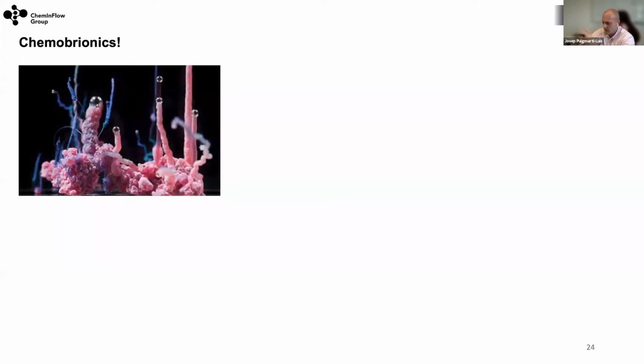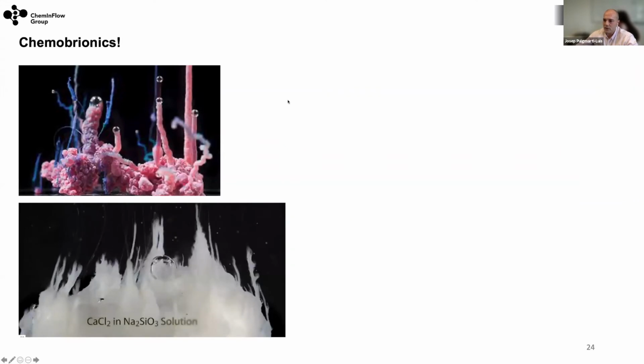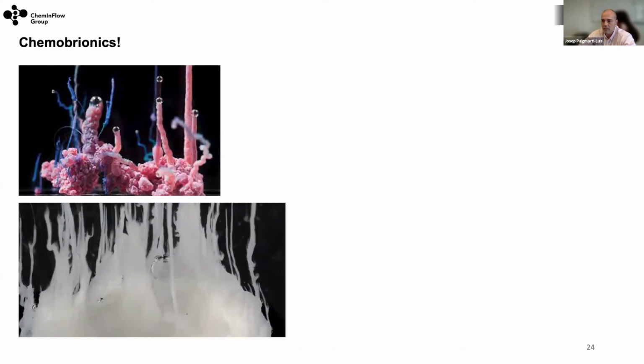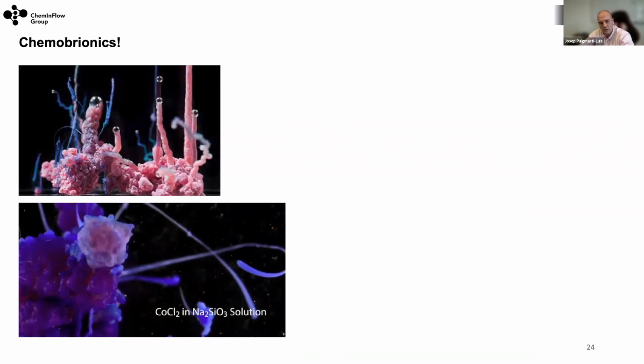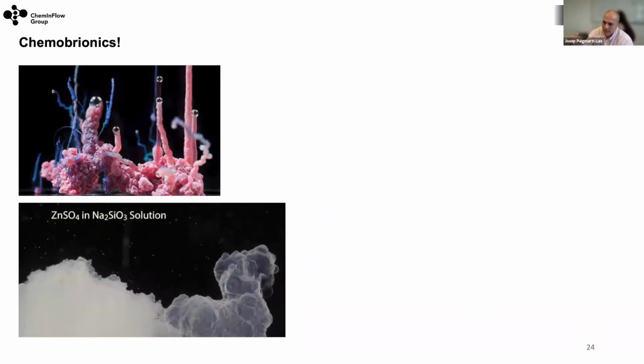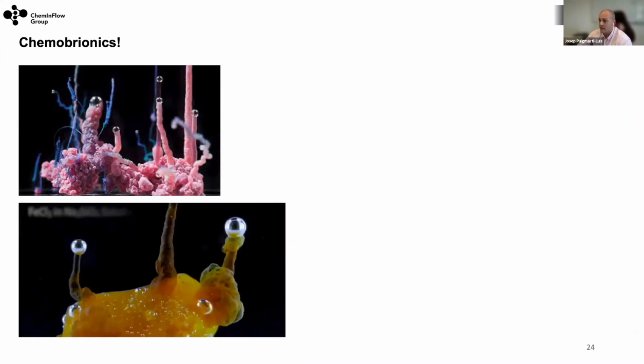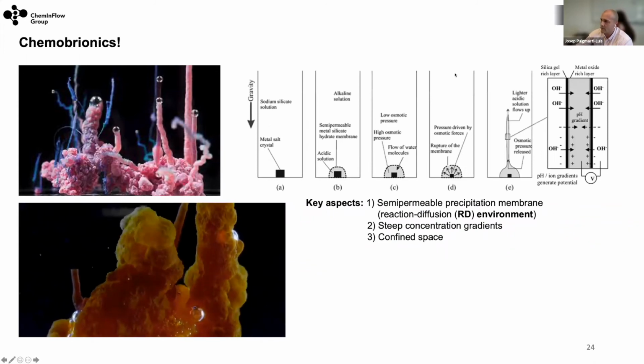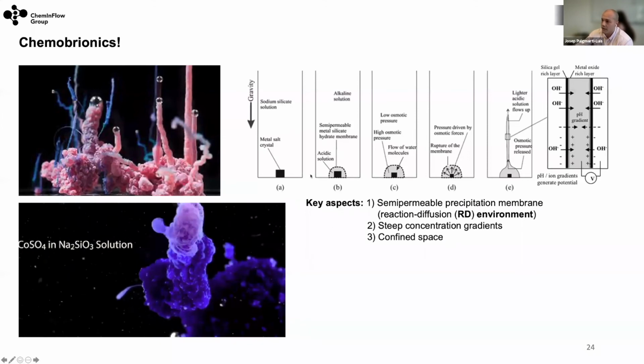So this is a chemical garden, okay? For a long time, people tried to understand how these structures are generated. What you see here is a movie of how these chemical gardens work. The research community was studying this for a long time because they thought that the origin of life emerged from this kind of chemistry. What you have here is the process explaining how these chemical gardens occur. In this case, you have the formation of a semi-permeable membrane that grows, and at some point it breaks. Then due to buoyancy forces, you have the formation of these columns that you see there. Here, you have a large differential potential. This is why people thought that this could lead to the origin of life, because it was possible to reduce, for example, CO2 and generate the first amino acids.